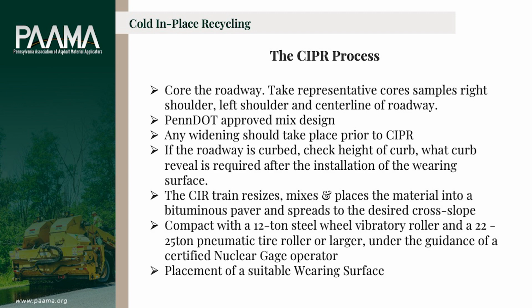If the roadway is curbed, check the height of the curb. What curb reveal do we need at the end of the project? Remembering that we're going to be putting maybe 1.5 inches of 9.5 millimeter on as the wearing surface. The recycling is a base course. The CIR train resizes and mixes in place the materials and then takes them and places them via a 2-stage conveyor system into a bituminous paver.